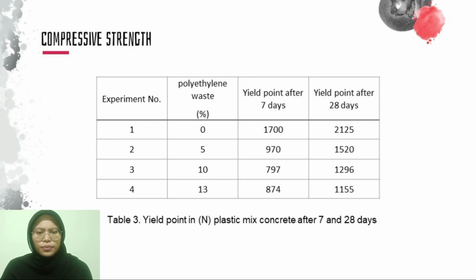Next, for the compressive strength result, table 3 shows that the yield points for various specimens were found to be in the range of 874 to 1,700 Newton after 7 days and 1,155 to 2,125 Newton after 28 days. It depends on the percentage of the fine polyethylene waste.